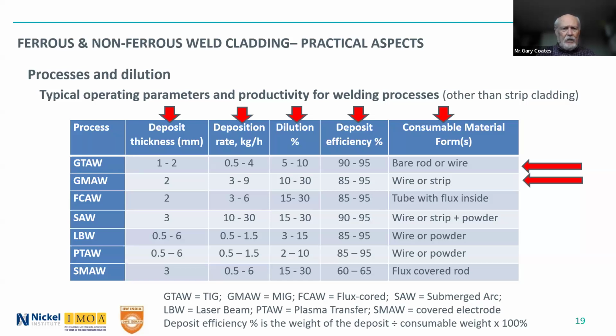If we take gas metal arc welding, and of course there are many different variations of that too, you get a little thicker deposit, you get much higher deposition rates, but you get higher dilution. And you can see when it says 10 to 30% dilution, you have to be very careful, because the welder might say, well, I can do it faster. I'll turn up the amperage on that, or the wire speed on that, to get it faster. But if he does that, he will get a higher dilution amount.